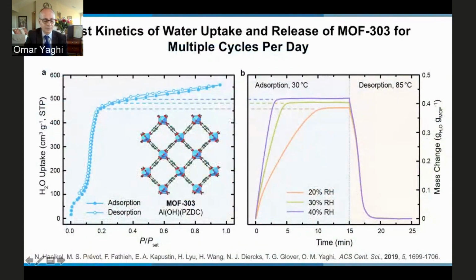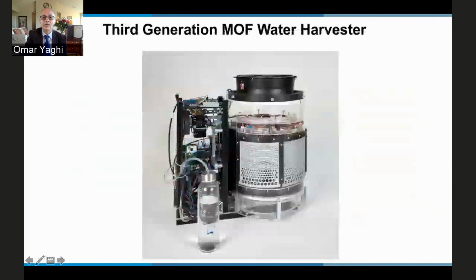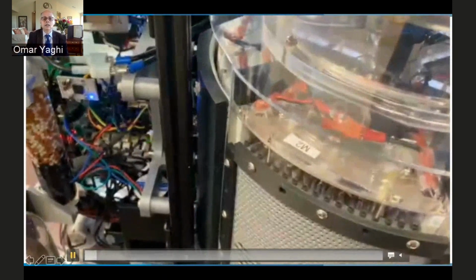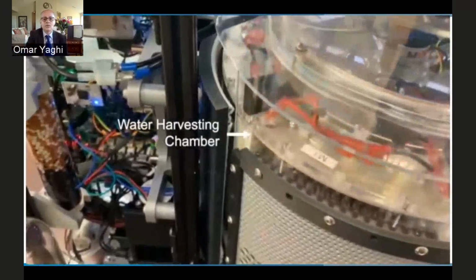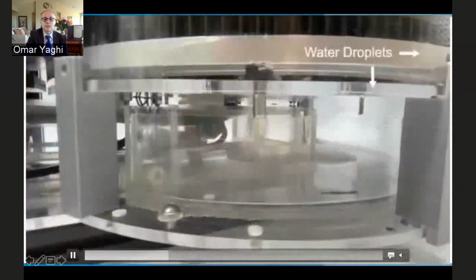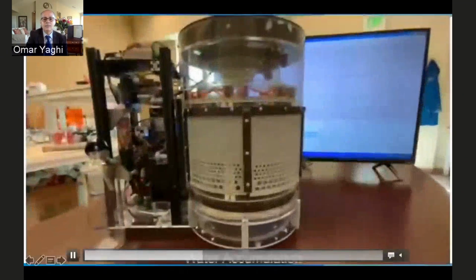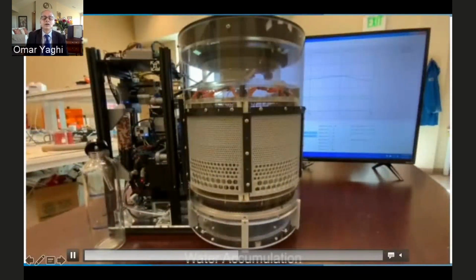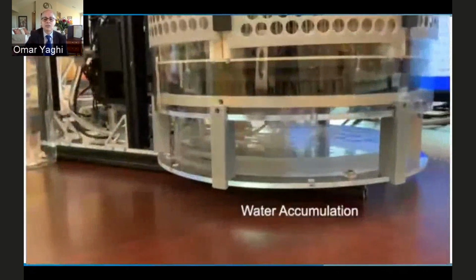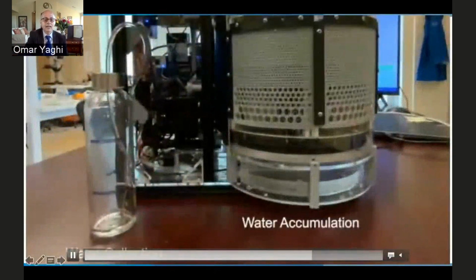So the beautiful thing about MOF 303 is that it releases water with great facility. You can see here that within less than 3 minutes, I can desorb all the water. And this allows us then to go to another water harvesting prototype that cycles through many cycles during the day. So this is a device that can take up water from low humidity, and it goes in through cartridges of MOFs. They take up water, you can see condensation there. And then these are the cartridges rotating. While one is taking up water, the other one is releasing water. The water is being accumulated here at the bottom and collected.